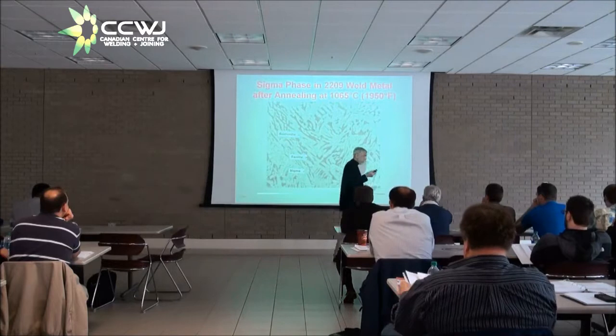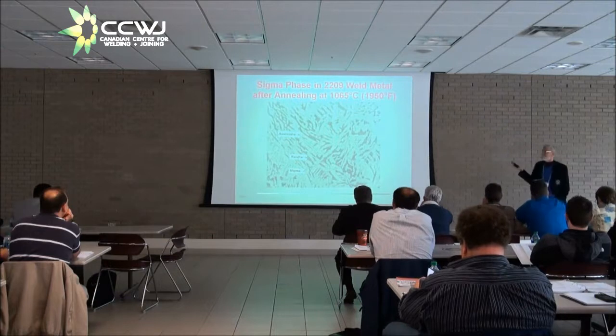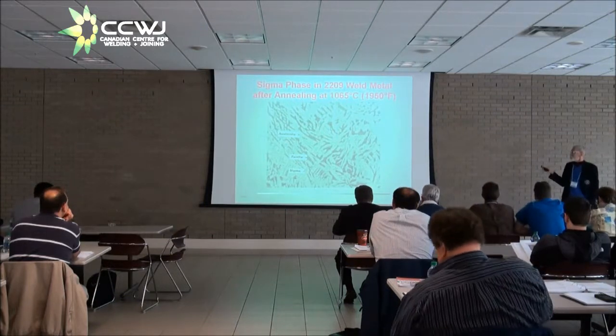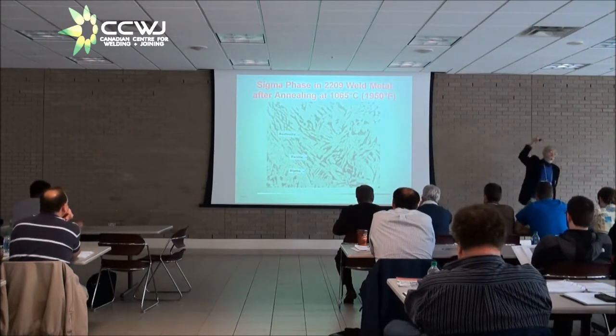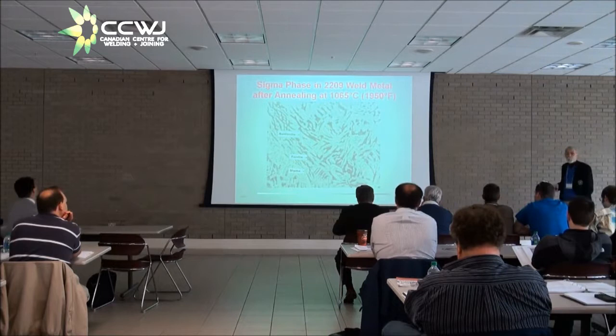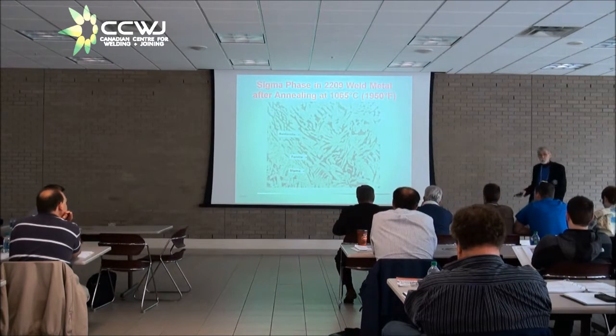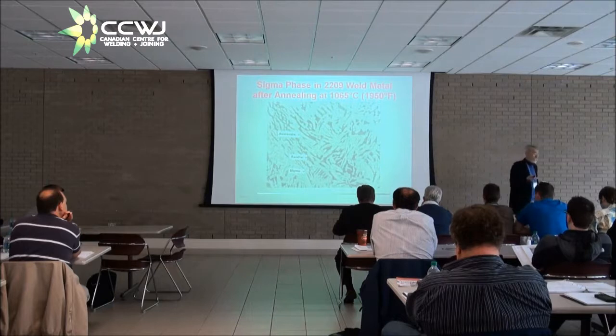Well, I was fooling around with duplex stainless filler metals at the same time, and I got to looking into heat treating of these things because I was making some filler metals for a purveyor of duplex castings. So I made a weld metal of a 2209 composition. I annealed it at 1065 degrees, which is 25 degrees higher than the ASTM recommended minimum. So I should have been safe. And I water quenched it. And I had Charpy specimens, tensile specimens, machined from it, and a metallographic specimen. Well, the first specimen that got addressed in my laboratory was the Charpy impact specimen.